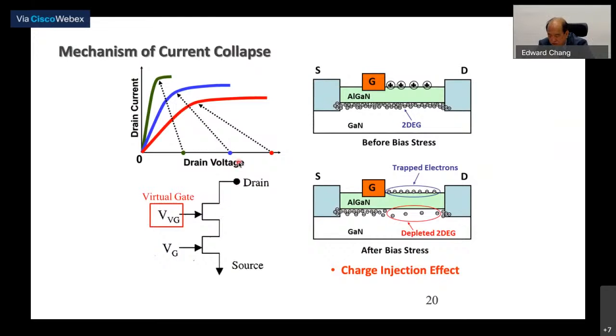And this happens because of trapping: after surface electrons drift to the 2DEG, there are a lot of positive ions on the top, and then electrons from the gate can be trapped at the surface, and that will deplete your 2DEG. And this is likely to happen if you don't control your surface really well, and the current will start to drop, okay, and then at high drain voltage, the current will drop even more, okay. So this is current collapse, okay.